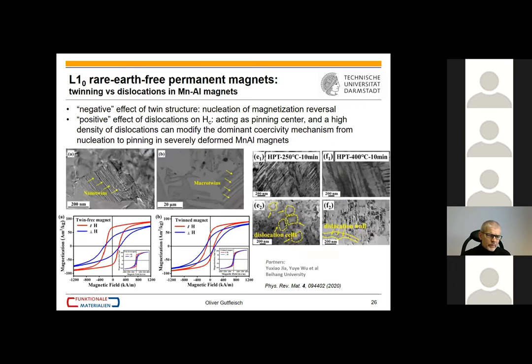Well, very briefly, this is manganese aluminium. Just to mention, I don't have time anymore, but what is happening here, we can induce dislocations by deformation, and we see a positive effect of the dislocation on coercivity, or vice versa, we see a negative effect of a twin structure, like shown before, on the coercivity. So it's a nice example of good and bad defects.